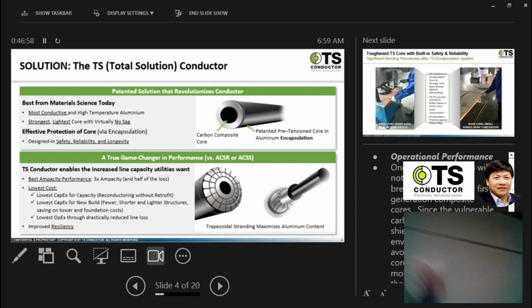We mentioned unidirectional composite has this limiting compressive strength from the ends or from bending. Now, if we can preserve pre-tension in the carbon core, imagine if you have the conductor bended. It does not automatically create compressive stress from bending, because you have to overcome the pre-existing tension before the material goes into compression, which is the vulnerability that this type of material has. So now you no longer have that compression vulnerability. We have a much better ability to handle sharp edge bending or small radius or angle changes in the field. That is the necessary robustness you need in terms of working with conductors.